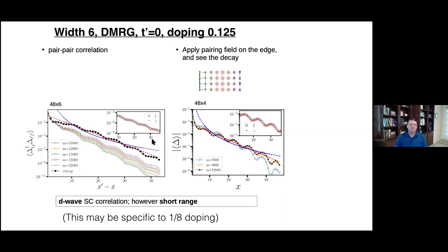There's two ways that we can do this. The pair-pair correlation is the less reliable, for some technical reasons. It's usually more reliable to apply a pair field along the edge and look at the decay. This will converge faster in DMRG, and the numbers are all bigger, so you can see things more clearly. The results are consistent with exponential decay of the pairing correlations. They are still of the D-wave form.